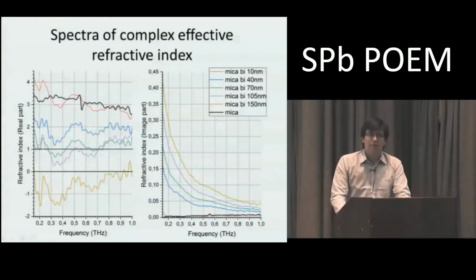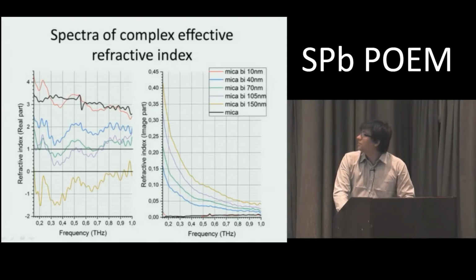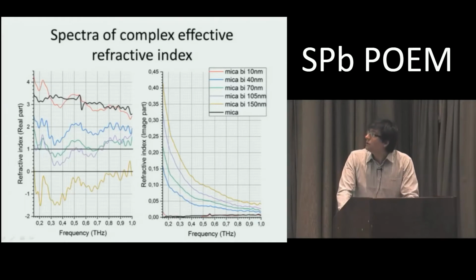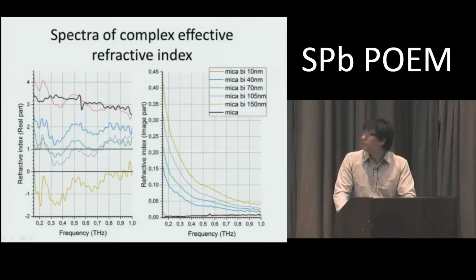We calculated the refractive index, and we show that the 10, 40 and 70 nanometer nanolayers of bismuth have a refractive index lower than 1, at 0.3 and 0.4, and the 150 nanometer layer has a negative refractive index in the real part. In the imaginary part, we see it increasing with increasing nanolayers.